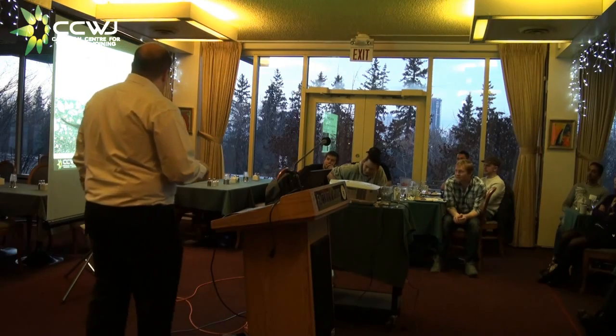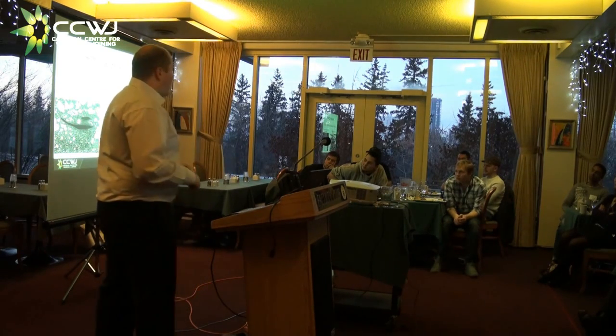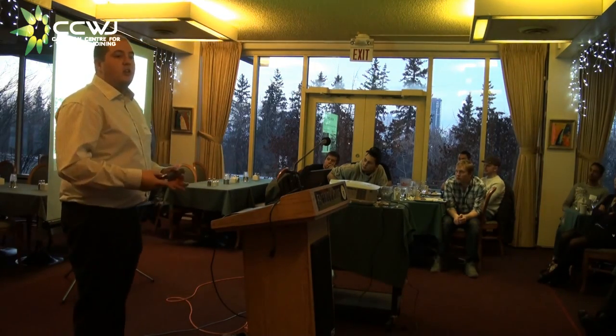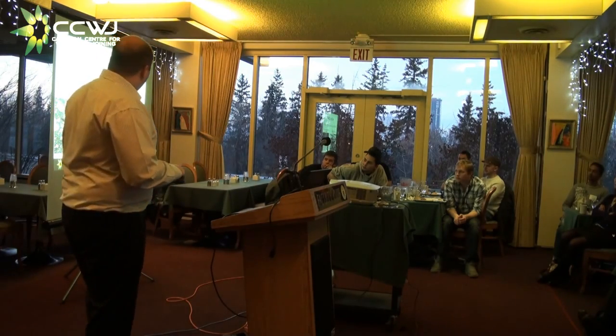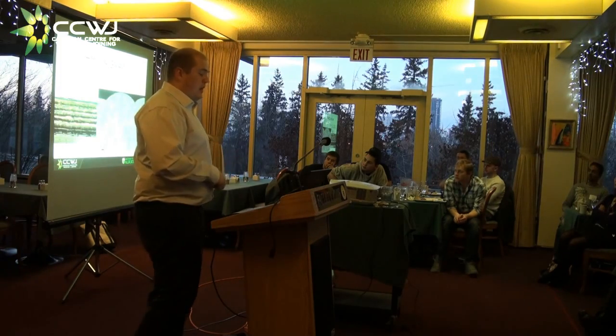And we see that around the tungsten carbides, we don't have any dissolution evident that we can see. And I've measured a couple spots around here. There's nothing. So everything is looking good.